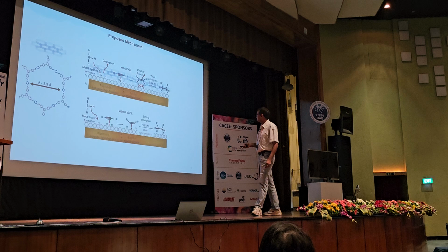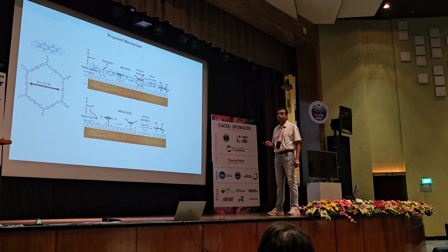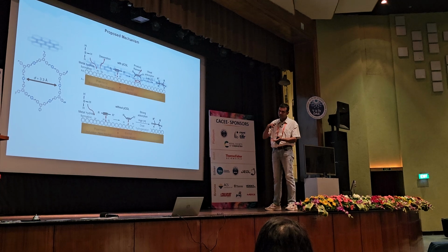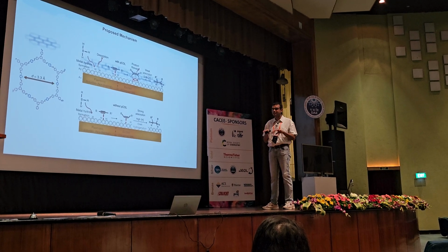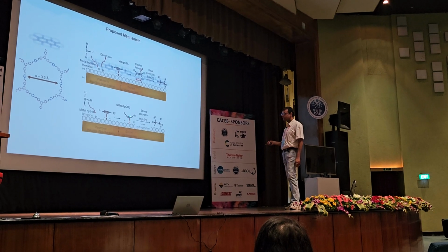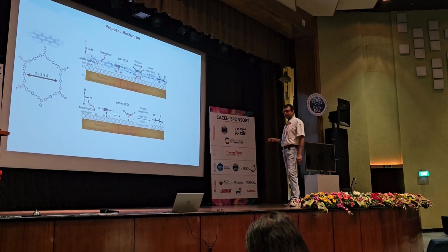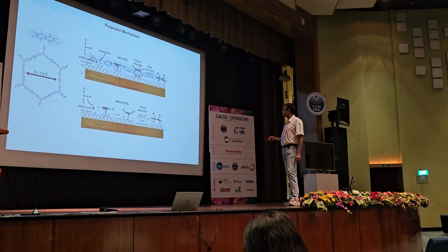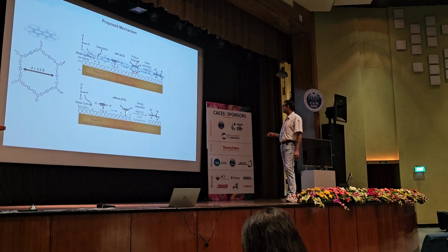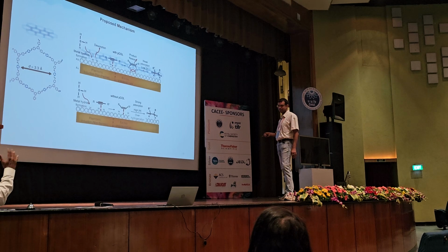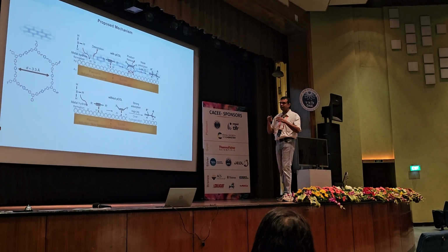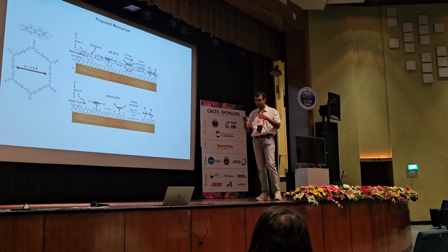We think that the polymer layer has a lot of nitrogens. Those nitrogens are electron donating in nature, so they make the surface very rich. The alkene is already very rich as compared to alkyne, so it changes the adsorption energy. Of course, it may not be well coordinated at this stage, maybe some sort of non-covalent interaction. Right now we are not able to resolve the steric and electronic effects very well.